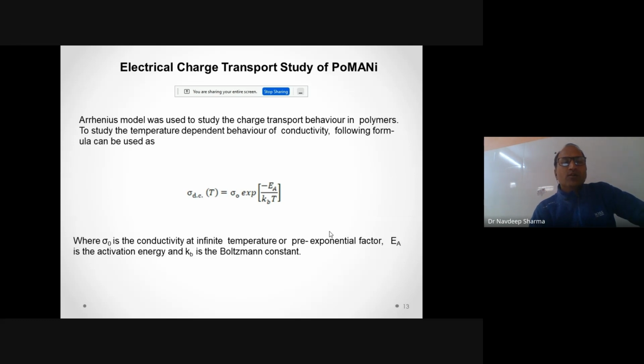The Arrhenius model is a very important model used to comprehend the charge transport behavior in polymers. This is the formula: sigma dc equals sigma naught exponential minus EA upon kB T, where EA is the activation energy, kB is the Boltzmann constant, T is the temperature, and sigma naught is the pre-exponential factor used to explain the charge transport behavior. Activation energy is very important here because it gives us the idea whether the charge carrier is moving in the polymer chain properly or not.